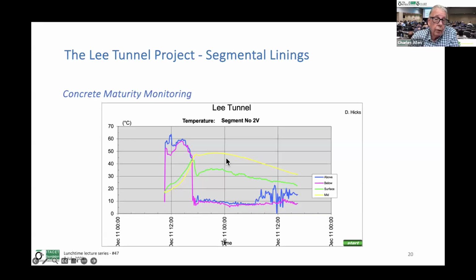Now, traditional thinking is that you take the temperature at the center of the segment and compare it with ambient temperature. Well, because of the heat flux coming out of the segments, the actual surface of the segment never actually gets to ambient temperature for at least 24, 36 hours after demolding. So we proved that this temperature differential, which was only maximum about 15 degrees, was totally acceptable and within specification limits. And so we allowed the precaster to actually move the segments to outdoor storage, even in the winter.